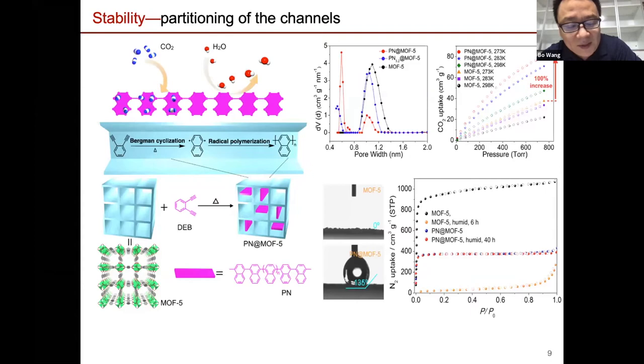But when we think about this zinc-oxygen bond by itself, it should be strong enough. The reason it's not water stable is that this bond is fully reversible. Water molecules attack the Zn4O cluster. So can we repel water from the pores to make it stable? The answer is yes. One simple way, inspired by Susumu's work, is to absorb the monomer inside the pore. In this case, instead of choosing other alkyne or alkene structures, we choose a dialkyne monomer through a very simple Bergman cyclization and then a radical polymerization.